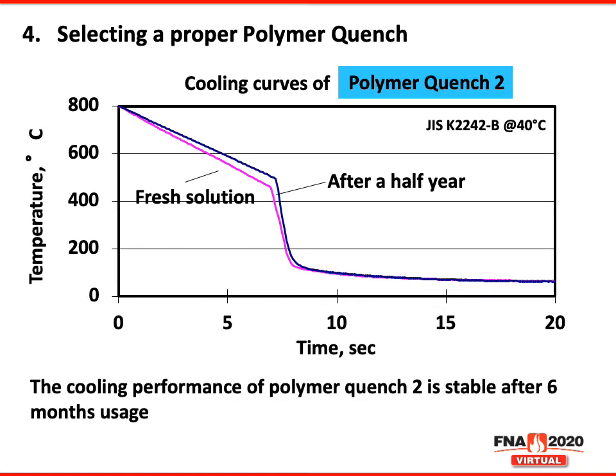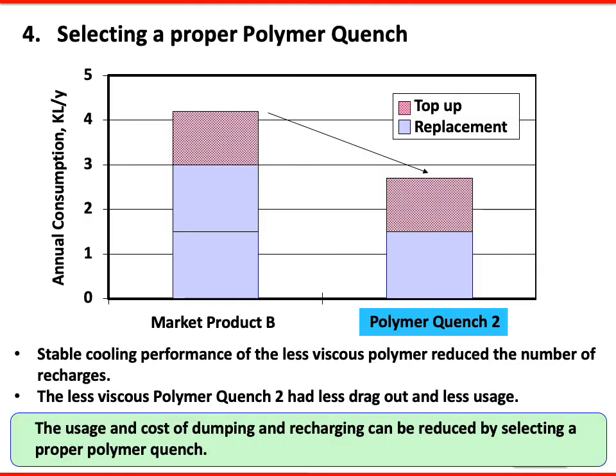And you can see here that after 6 months, the cooling curve is relatively the same for Polymer Quench 2 with the short polymer chain and less viscosity. Also, because the cooling performance didn't change over that 6-month period, it didn't have to be dumped and recharged. Because it's less viscous, it goes back into solution much easier. It doesn't require the shear and agitation that a thicker, heavier, more viscous polymer will.